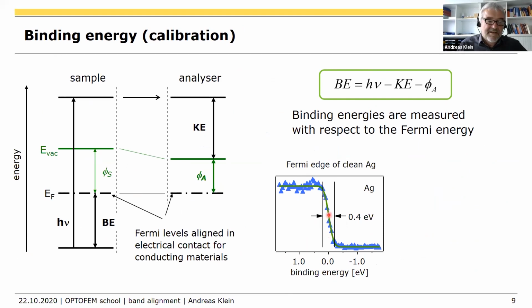We take a silver sample, and we can really quantify the kinetic energy, which corresponds exactly to the position of the Fermi energy. If we remove our metallic sample and we put a semiconductor sample there, the Fermi level is still there because everything is always in electrical contact with the XPS system, with the manipulator. And this always has the same Fermi level. It doesn't change when you put another sample there. You only have to make sure that you have an electric contact between your sample and the manipulator. And then the Fermi levels between the manipulator and the sample are aligned.